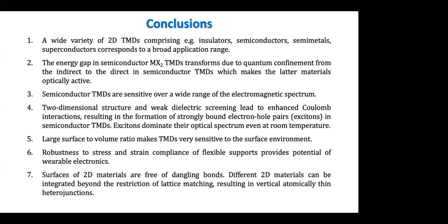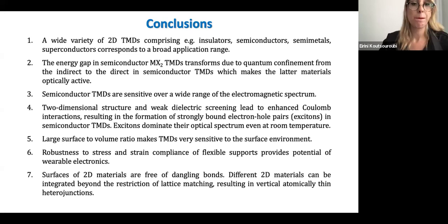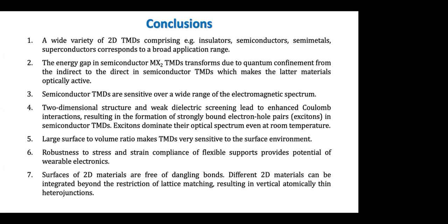Yes, if we think about the energy of an exciton, it is because of electrical, Coulomb interactions. And the Coulomb potential depends on the dielectric constant of the material in which the exciton exists. So if you change the environment, you change the dielectric constant and you change the energy. Of course, there are also other issues, as for example, the roughness of the silicon oxide substrate. But I would say mostly this is because of the electrostatics.